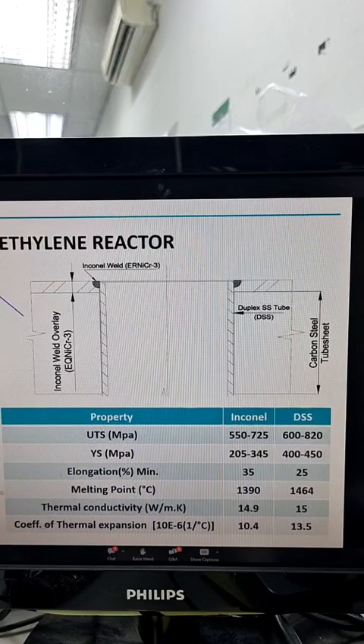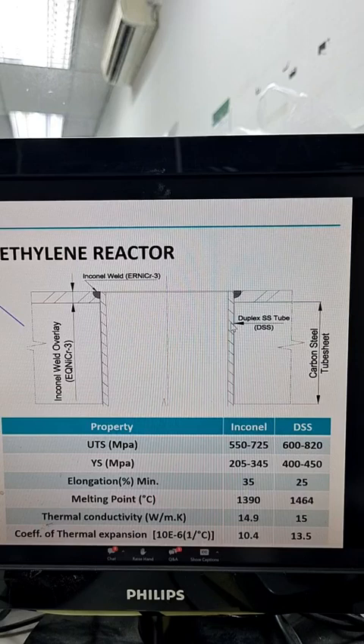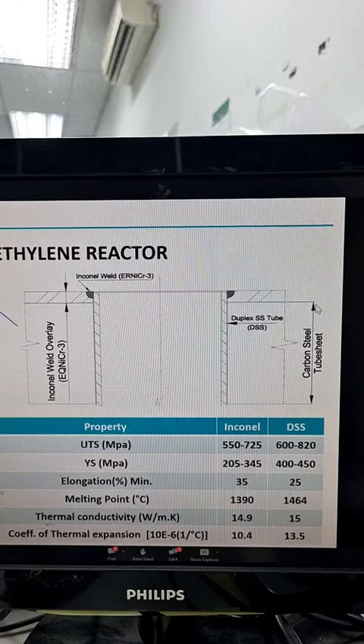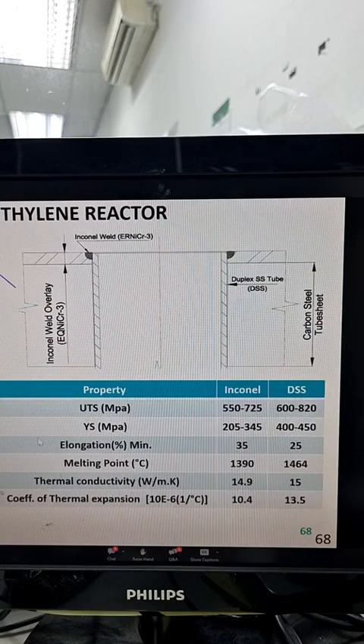This is another example in a reactor where you have very critical tube sheet welds, where there is an overlay of Inconel on the tube sheet and your tubes are of duplex. So it becomes much more complicated. How do you join a duplex to a carbon steel? Generally these are done with Inconel 600, and you see the difference again in the basic physical properties and the mechanical properties as shown in this table.